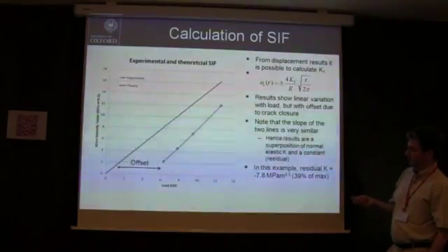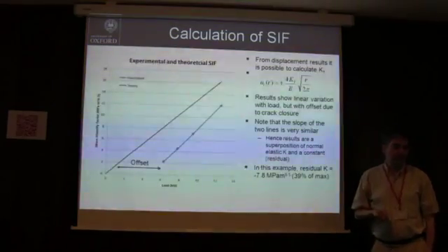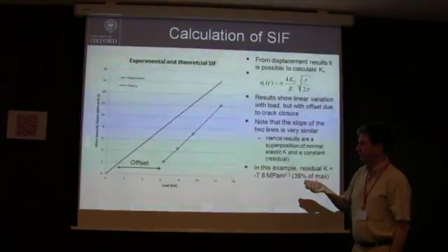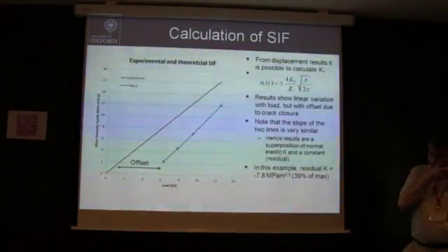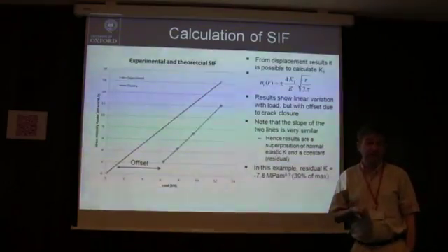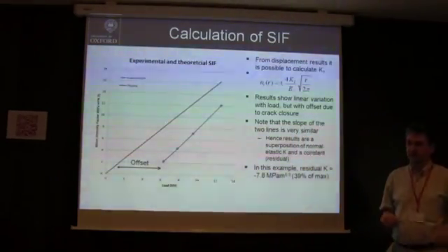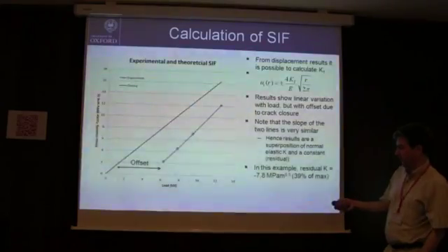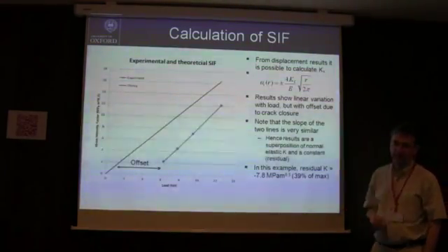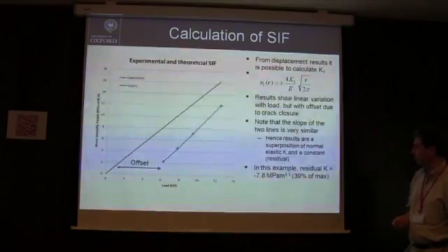So what you see is that for any particular load, there's a reduction in stress intensity factor, which is a residual negative stress intensity factor, caused by crack closure, or if you prefer to think of it otherwise, by the residual stress field around the crack. Essentially, until you've applied a load of this much, nothing happens, and then the crack opens, and then we get essentially a linear elastic response, and that's fine.